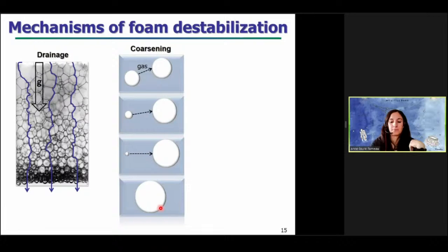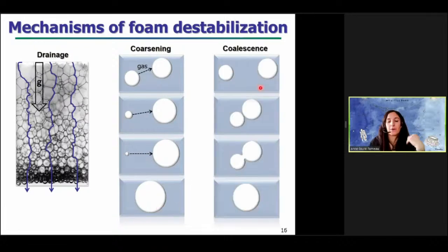The third one is called coalescence. When you have two bubbles that come into close contact, the thin film between the bubbles can break, and the two bubbles reorganize to form one single bubble. So again, the result is an increase of the bubble size with time. And when this phenomenon of coalescence happens at the top of the foam, you also observe a decrease of the foam volume with time. So if you want to have a stable foam, you need to almost stop these three main mechanisms of foam destabilization.